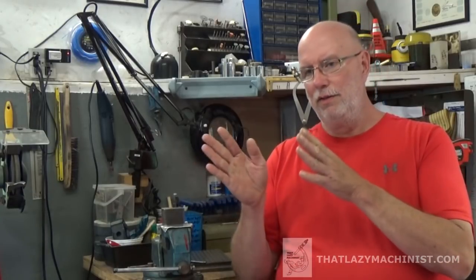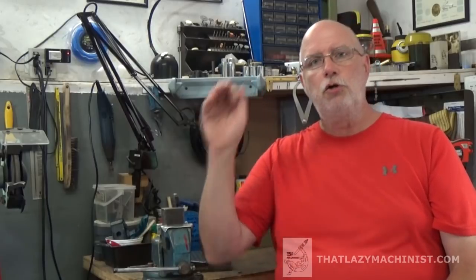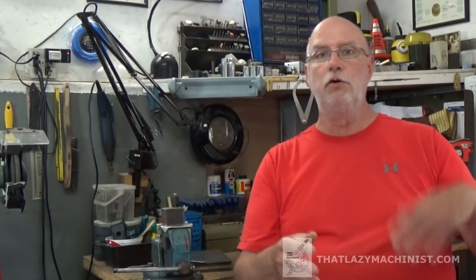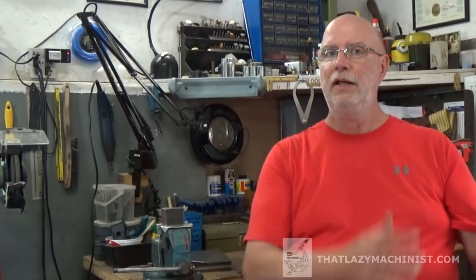So that is why the blacksmith double dips. He needs or she needs to cool the part as quickly as possible because of the quantities of iron that is in the part. Now, we said that 0 to 0.3% of carbon in steel is a low carbon steel, and they're generally considered to not be hardenable. However, even if I have a 0.2% carbon, so clearly in the low carbon steel zone, if I can cool it down quick enough, I will get a certain amount of hardness, but I will not get very much penetration.